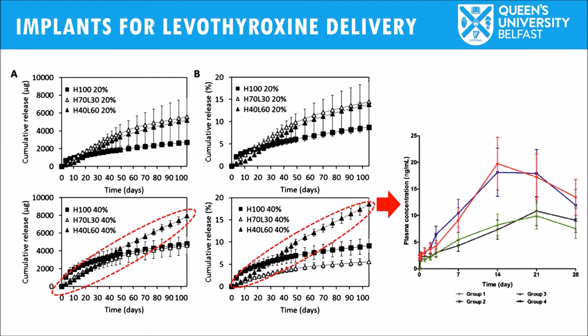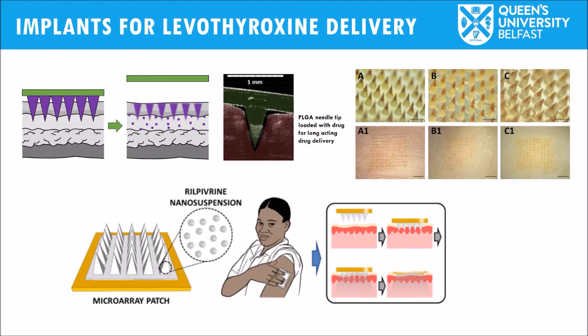Specifically, the size of the implants, based on these results, will not be 10 times smaller, sorry, that I mentioned just a couple of minutes ago. It will be between 5 and 14 times smaller than the ones that we applied into the rats. I mentioned that minimally invasive systems can be used for the implantation of small implants. That's the idea that was suggested by the results obtained in the levothyroxine implant animal experiments. So a potential technology that can be used for this is microneedle technology. Microneedle technology can be used to implant little implants made of biodegradable polymers like PLGA.